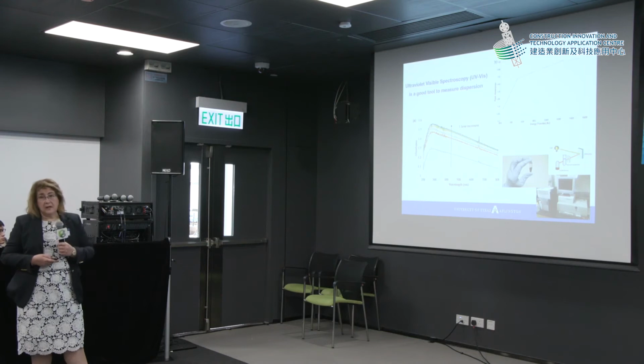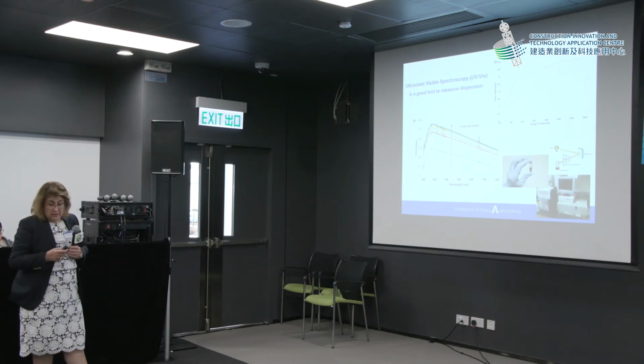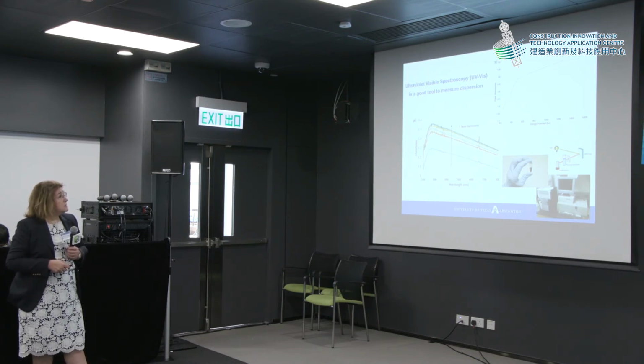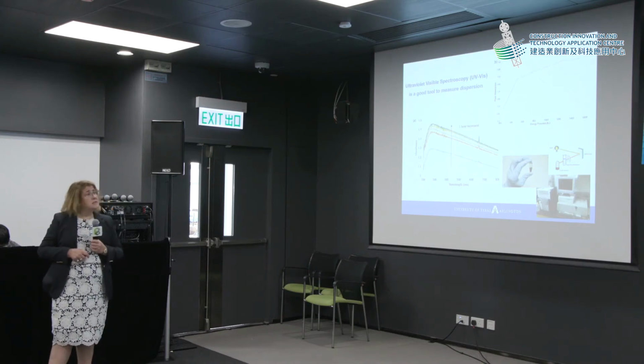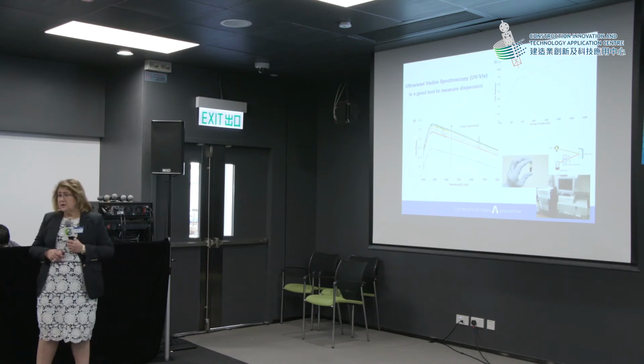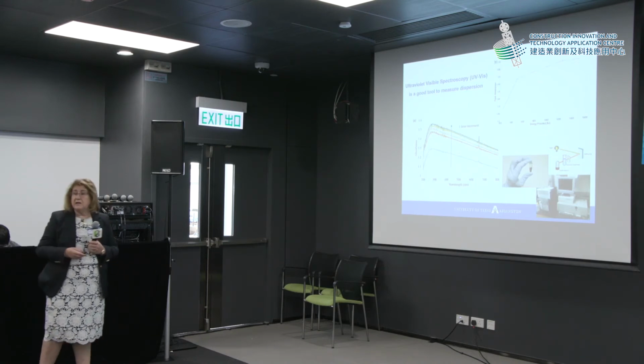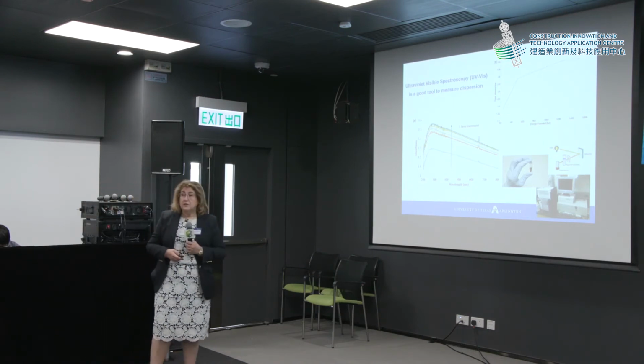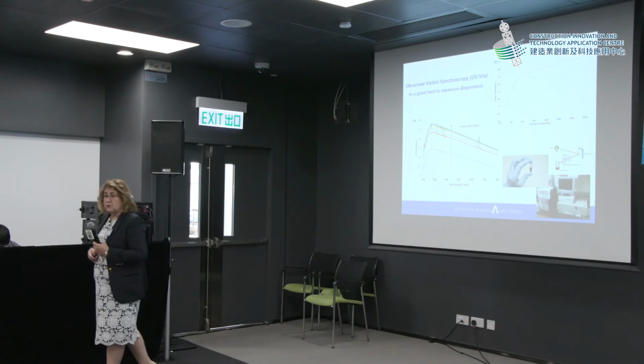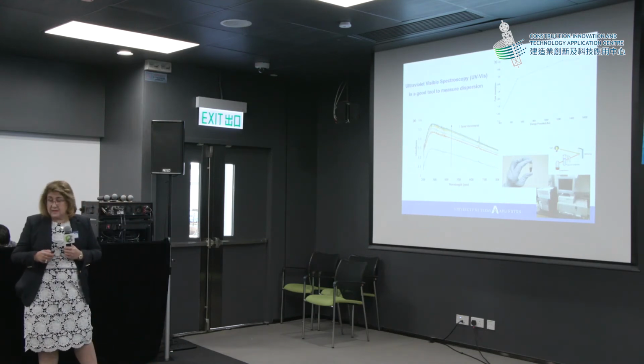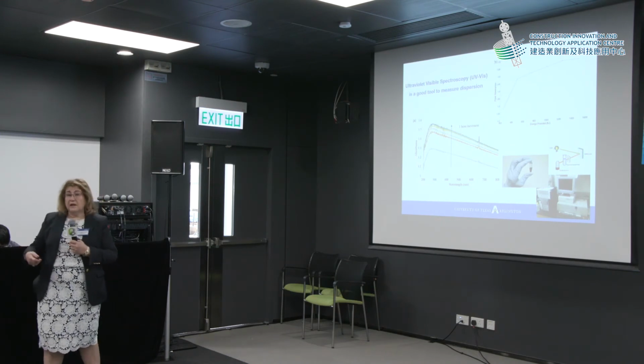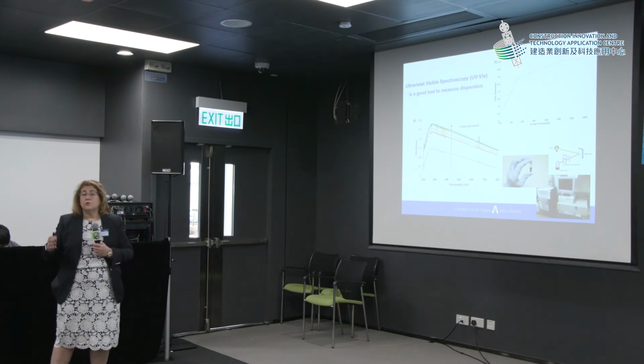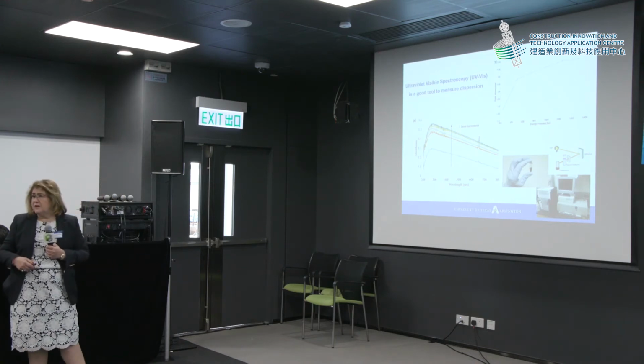If we want to check the dispersion, we have better ways of checking it. For example, we use UV-vis, ultraviolet visible spectroscopy, and we are able to establish a relationship between the peak of the light that is being transmitted in our dispersions and the energy that is provided to the dispersion, so that we can have an effective dispersion and not have breakage of the nanotubes or the nanofibers inside the mix. Providing higher energy than necessary, we saw that we are cutting the nanotubes in half,